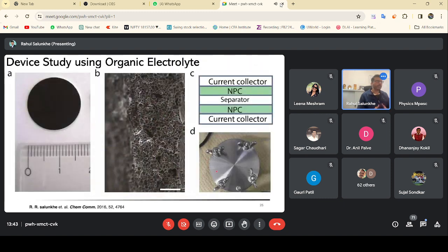Now, to further enhance the electrochemical performance, for the device study using organic electrolytes, we have developed this kind of a coin cell type supercapacitor testing assembly, and this is the typical structure where on both sides we have a current collector, nanoporous carbon. This is a typical structure of carbon coated on the stainless steel substrate, and here is the cross section, and we can see that it is nanoporous carbon coated on the current collectors, separated by a separator and the electrolyte, and this whole assembly is put in the coin cell, and we have measured this performance in organic electrolyte NEt4BF4 in propylene carbonate.